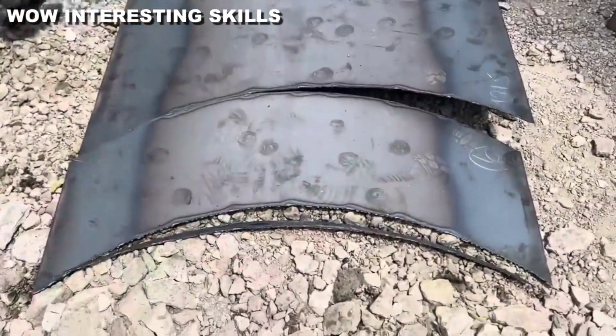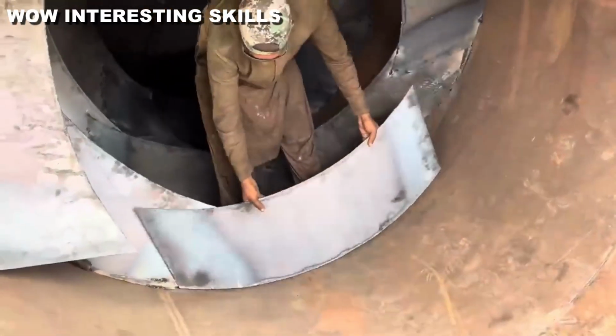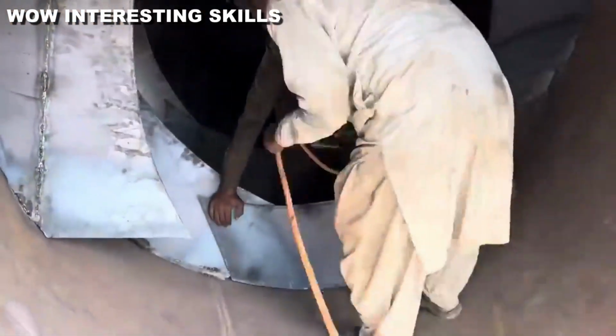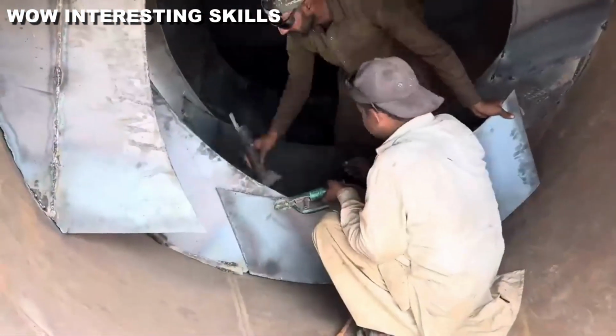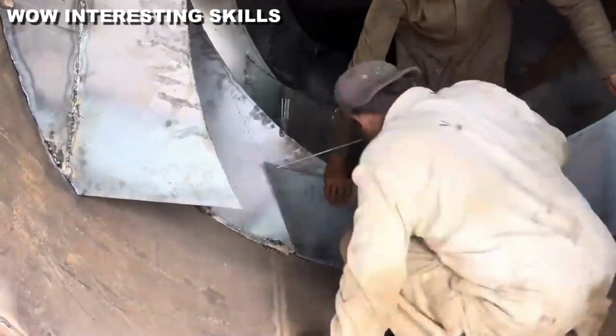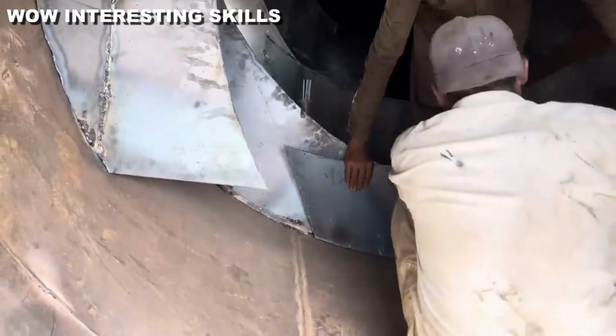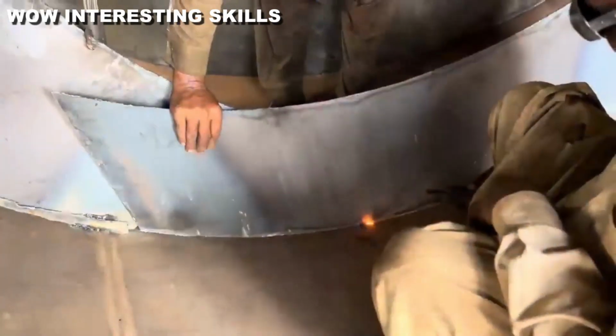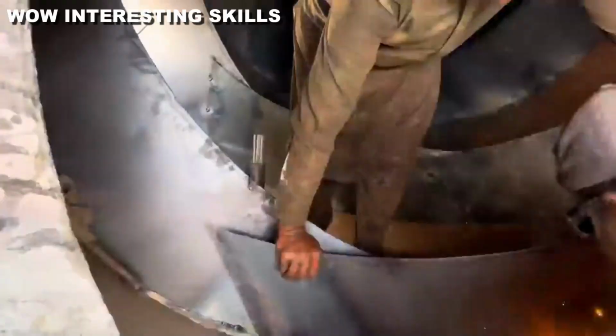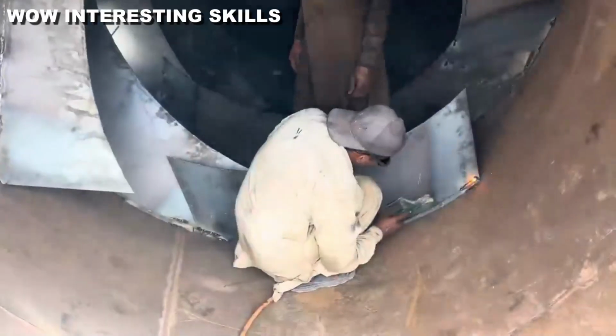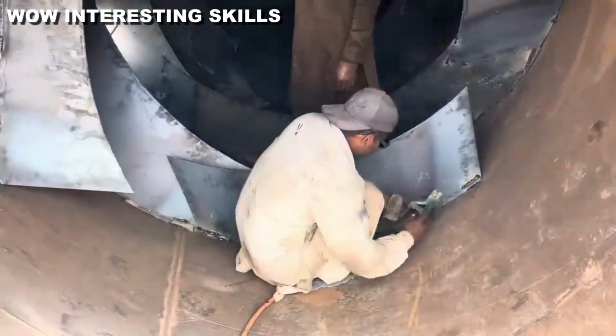As the drum spins, centrifugal force drives the concrete outward, pressing it firmly against the inner drum wall. This creates powerful radial pressure that directly impacts the surface area of the helical blades. As a result, the blades experience considerable sideways stress, which attempts to bend or distort them outward.